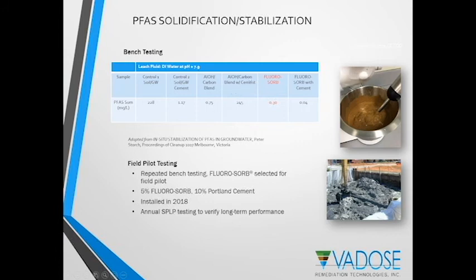But interestingly, when that was blended with cement, in fact, the leachable PFAS was higher than the control sample. It's an interesting phenomenon we'll see again, and we'll talk about what that might be. We think this to be either an effect of pH or possibly the heat of hydration causing some volatilization of these PFAS compounds. When Fluoro Zorb was added, the total PFAS was able to be reduced to 0.3 milligrams per liter, and Fluoro Zorb and cement had the best performance at 0.04 milligrams per liter.